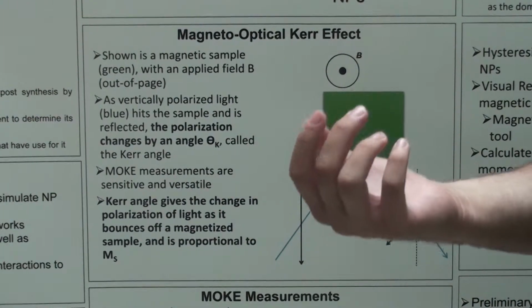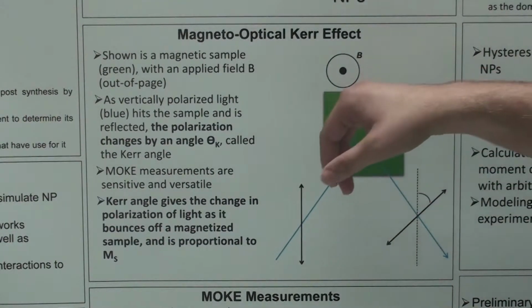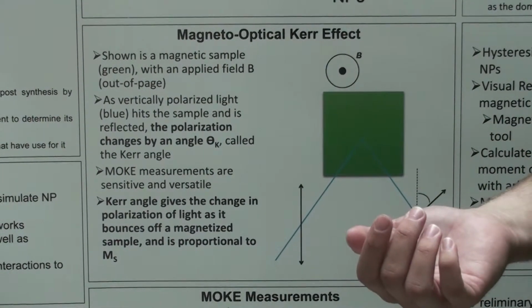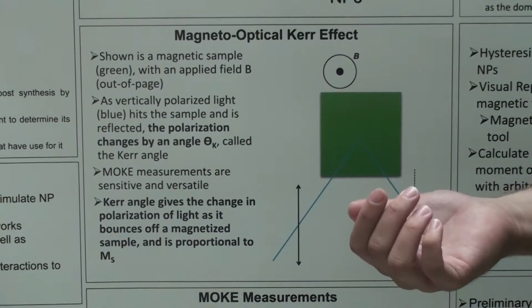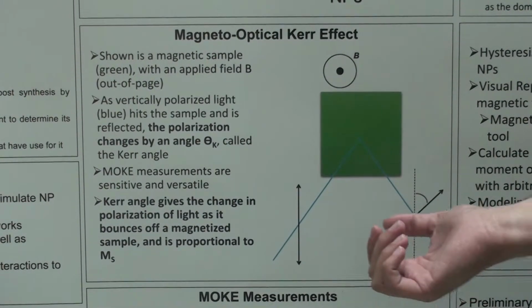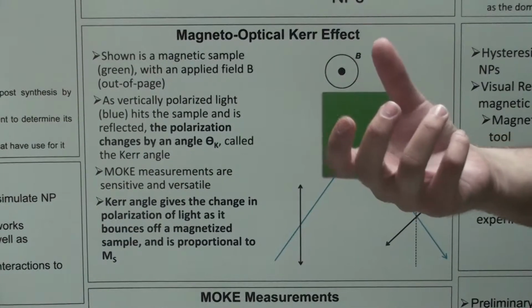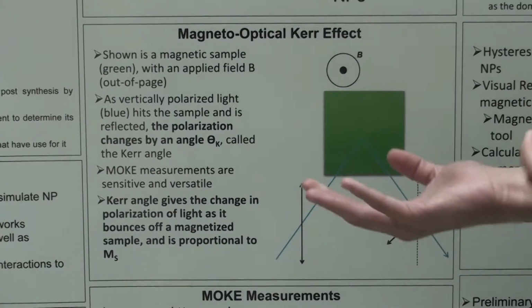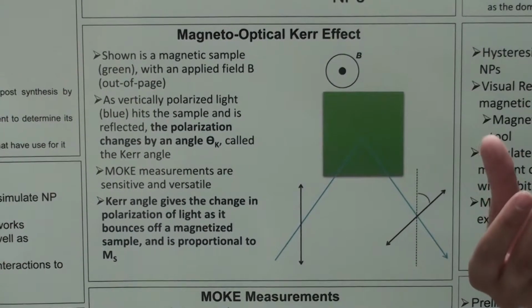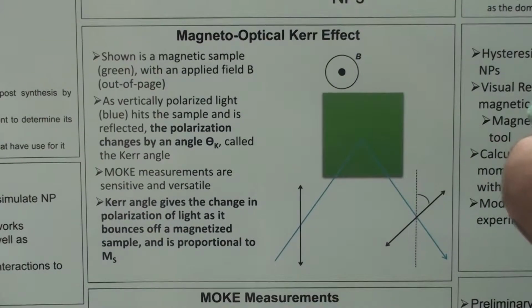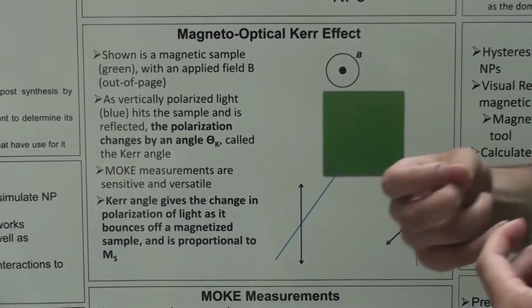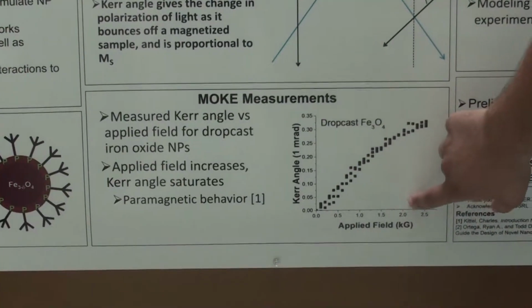Unfortunately, a lot of times when you do this experiment, you have to do it with iron oxide nanoparticles in liquid crystal. Now, liquid crystal is also birefringent, which means that it affects the polarization of light itself. So what you end up with is a convoluted signal in which you get a contribution from the iron oxide nanoparticles as well as the liquid crystal. So this would be useful in that it would help you deconvolute the signal and take out the noise from the liquid crystal. And here we have some preliminary data from these MOKE measurements.